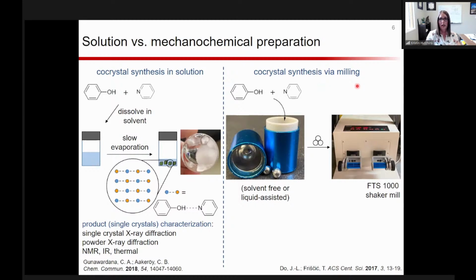The second way, which is going to be a lot of the focus of today's talk, is actually making co-crystals via mechanochemistry or via milling. Mechanochemistry is really simple in that you could actually just use a mortar and pestle, which most people have in their lab, to make co-crystals. So you would just manually grind the 2 components together. In my lab, we actually have a shaker mill. This is our Formtech Scientific 1000 shaker mill. And so we do this in an automated process instead of by hand.